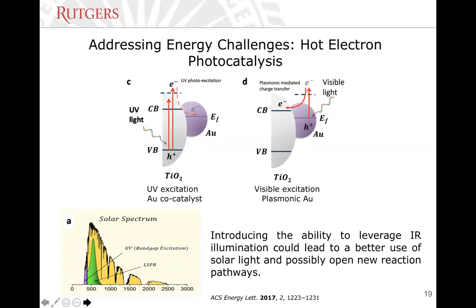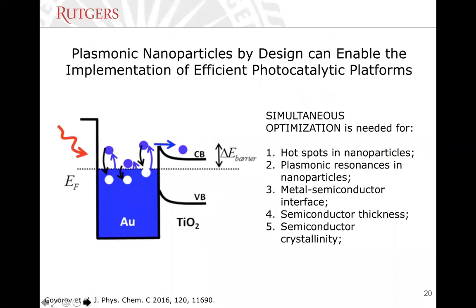And so we decided to find a way in which, by leveraging the gold nanostars, we can absorb radiation across the broad spectrum, well into the near infrared or infrared, and do the same thing. To do that, we had to really optimize materials design rules. And we did it this way. The first thought we had was, if we have a macroscopic or microscopic TiO2 catalyst and we decorate it with nanoparticles, in the ideal case that the nanoparticle is spherical, we would have only one point of contact, right? From which the electrons can be extracted into TiO2 from the nanoparticle. We know it's not the case because the nanoparticles are multifaceted, but yet the points of contact would be minimal. So our idea was, how about we take the nanostars and we actually coat them with TiO2? Can we do that? In that case, we have perfect contact everywhere, and any electron that is generated, we can take it out.